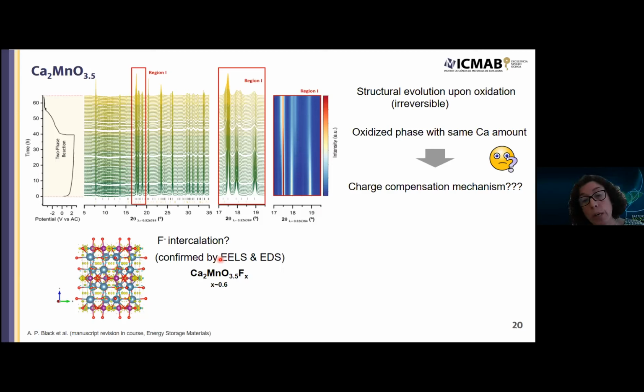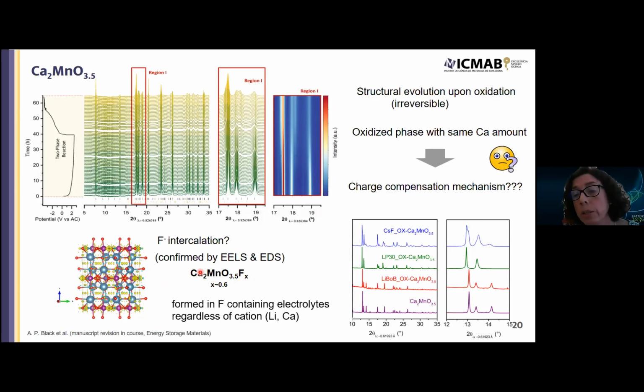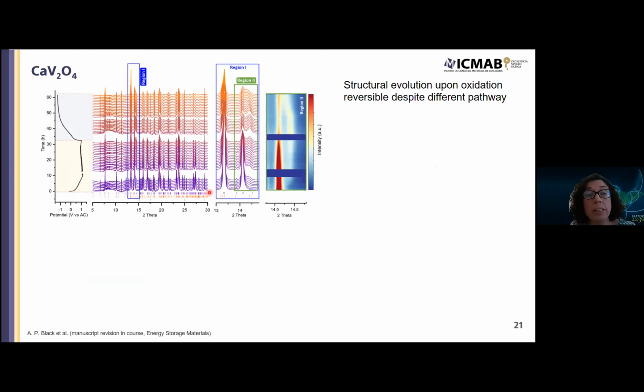We confirmed the presence of fluorine by XPS and EDX, and we were able to even estimate the amount, which would be about 0.6, which would be in agreement with not only this position being filled, but also a small amount of fluorine there. And the definite proof that this was fluorine due to electrolyte decomposition was that we performed different electrochemical oxidations in other electrolytes containing or not fluorine. And for instance, when we use LiBOB, which does not contain any fluorine, we don't see any changes in the diffraction pattern. But when we use LiPF6, which contains fluorine, or even cesium fluoride, we do see this oxidation. So indeed, what happens here is that when we oxidize the compounds, we get intercalation of fluorine. So this will not be useful as a positive electrode for calcium batteries. And finally, the last compound.